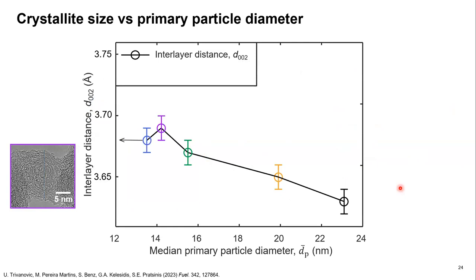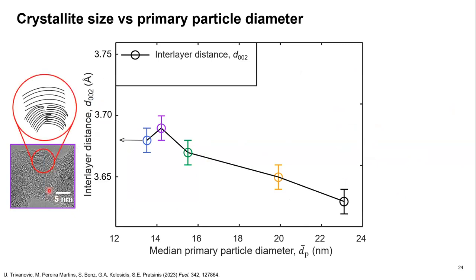We wanted to take this one step further and analyze the particles using X-ray diffraction. What X-ray diffraction allows us to see is that within a single primary particle, we have these crystallite regions. And the first thing that we can extract from the XRD is the interlayer distance. So this is the distance between the individual layers of graphene. As we can see on the left-hand y-axis here, we have the interlayer distance plotted against the median primary particle diameter, and we do see a slight decrease in the distance between the layers as we go from smaller to larger primary particle sizes.